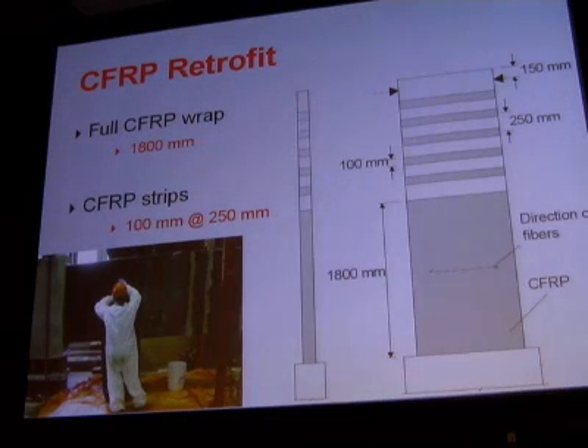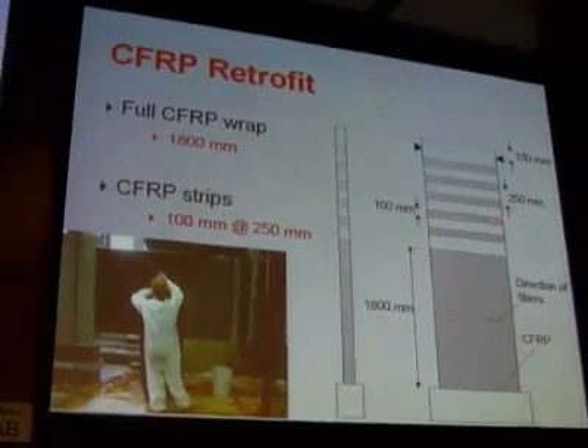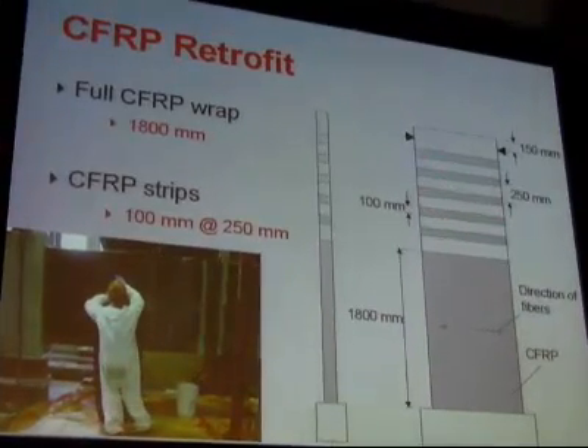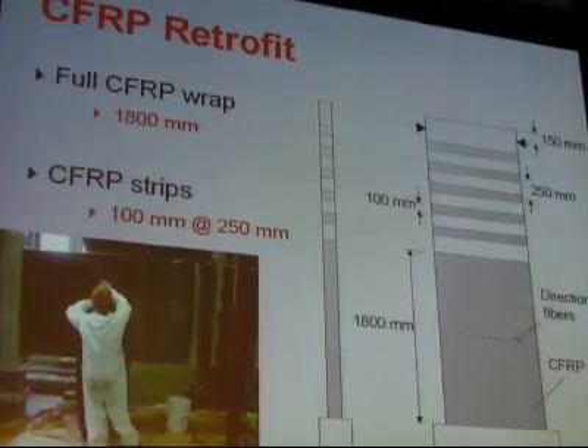Well, we looked at a number of ways of improving this. As I said, the walls were tested in their horizontal position, and we used carbon fiber wrap. We rounded the corners, we roughened the surface, and then you can wrap the carbon fiber around the walls. It's a very easy solution. We did it over the probable plastic hinge region with a little bit of extra. We used the carbon fiber wrap with the fibers in this direction, of course, in strips as well to give improved shear response.